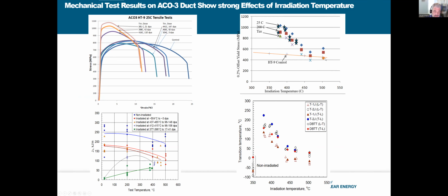And if you put all the data together, you can sort of see that here in this plot of 0.2% offset yield stress versus irradiation temperature. At the higher irradiation temperature, above 420-ish C, there really isn't much change in yield stress at all. But as you decrease the temperature to 400 C and below, you get significant hardening in this material, which leads to a reduction in the fracture toughness, which is shown here.